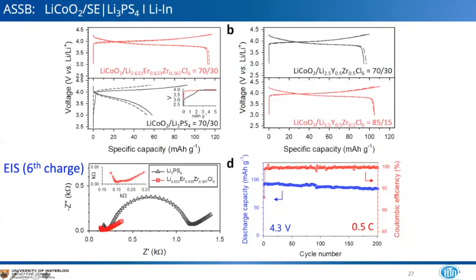And we then looked at this material with lithium cobalt oxide as a positive electrode. This shows the data for the erbium and for the yttrium. And you can see that, especially in the case of the yttrium, we're able to obtain rather good electrochemical performance with as little as 15% of the electrolyte. And especially you can see in the impedance data, the EIS, we have reduced charge transfer for the halide compared to a solid electrolyte where we're using just lithium phosphate, and that's less than 1/20. So we've really decreased that interfacial impedance dramatically in the cell.